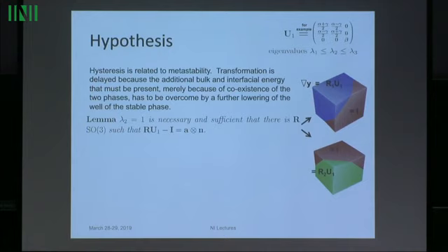You make the austenite phase perfectly compatible with the martensite phase, with a single variant of the martensite phase. Okay? And how do you do that? You make the middle eigenvalue of this matrix, this is the transformation stretch matrix, which maps one crystal structure into another, equal to 1.